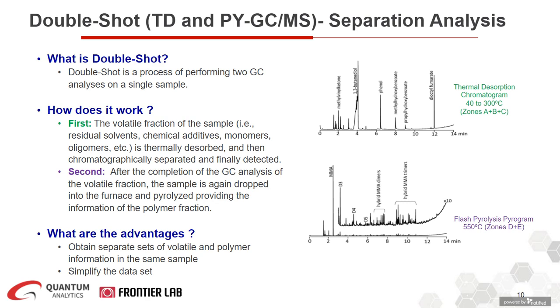So performing double shot on an eyeliner using our obtained EGA, we were able to identify the optimal temperatures and separate the additives and volatile compounds from the polymeric portion of the sample. What are the advantages? Obtaining separate sets of volatile and polymeric information from the same sample, which can really simplify the data analysis of your sample.